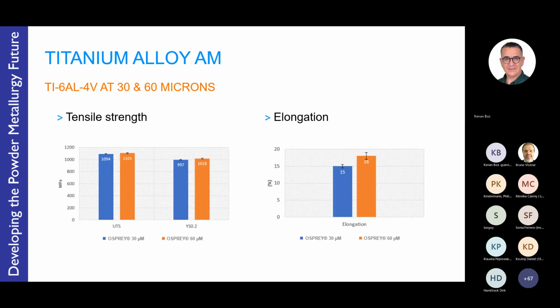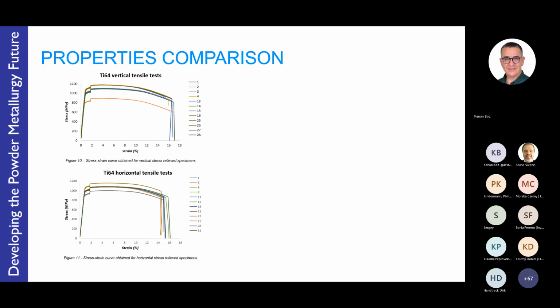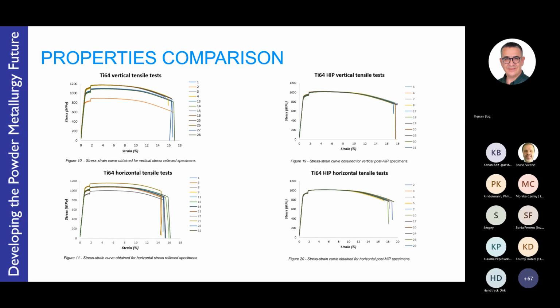And then when we have powders produced at different layer thicknesses, 30 microns and 60 microns, little difference between the mechanical performance, slightly better perhaps when it's at 30 microns, and the elongation actually slightly better when it's a 60 micron layer thickness. And then comparing the properties, here we have the tensile test for titanium 6-4, and there's definitely advantage for hot isostatically pressing. Not so much in increasing performance, but in fact in improving the reliability of the statistics. So it reduces the variability of the titanium.